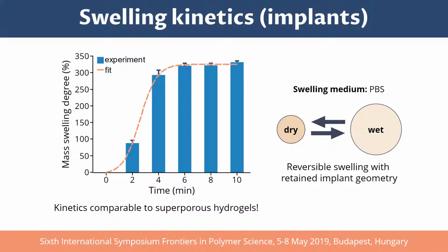Swelling kinetics of the implants was quite fast and even comparable with some superporous hydrogels. Equilibrium swelling degree in PBS was reached within 6 minutes. The swelling was reversible and the implant retained its geometry during the entire process. Described swelling behavior of the implant is suitable for clinical use since it can be stored in the dry state and rapidly rehydrated when necessary.